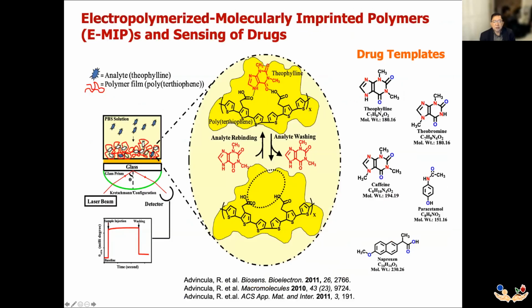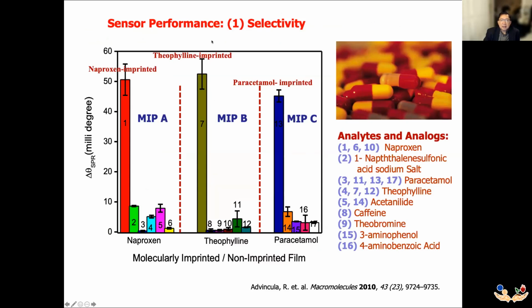and selectivity. So in this first example, you can see how we tried to template different drugs, whether it's theophylline or paracetamol or naproxen. We use polythiophene as a matrix or a monomer to surround the original template, electropolymerized it on top of the gold surface for a surface plasmon resonance detector scheme. And then, as you can see here, this system has a very high selectivity to the original template, which was used for making the sensor, whereas the rest were left behind. So you can see how powerful it is to use the lock and key mechanism to design artificial sensors based on electro